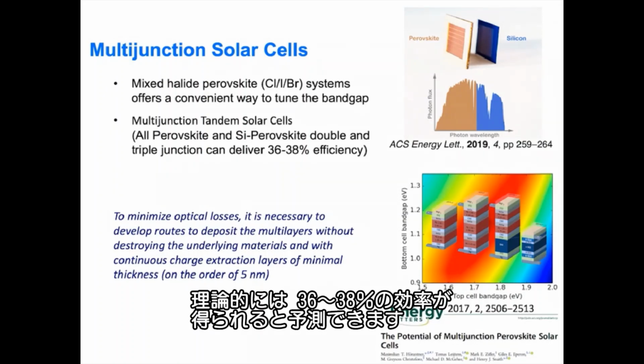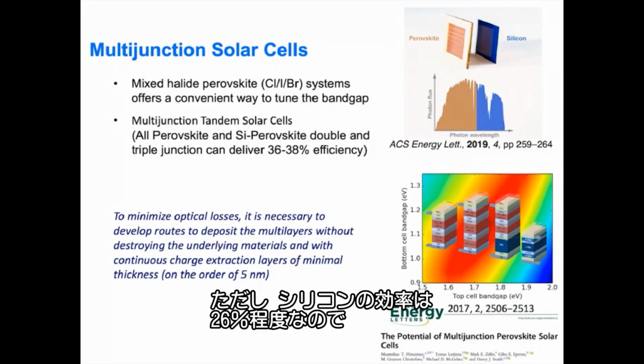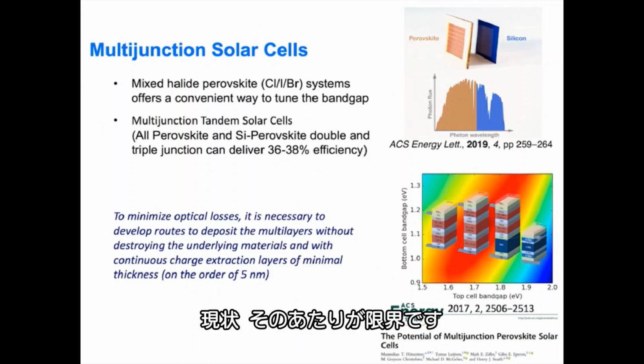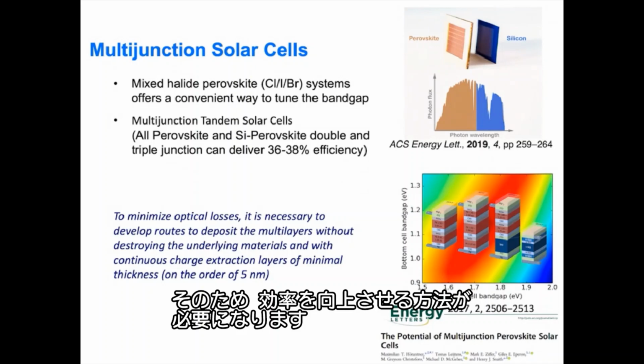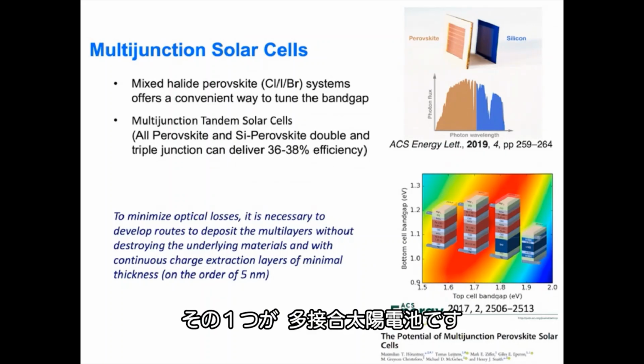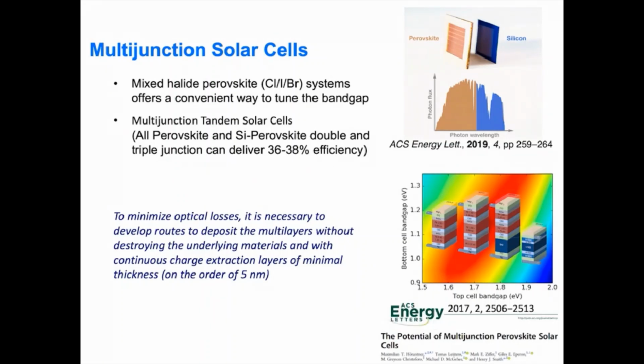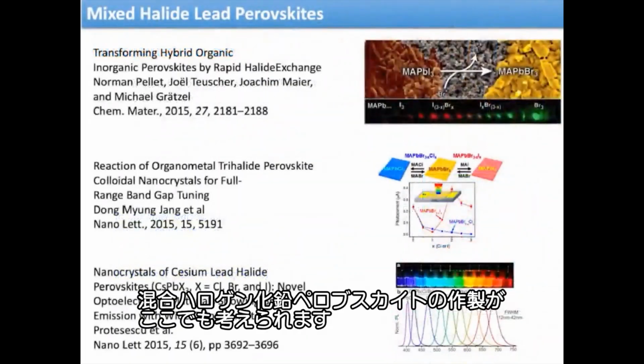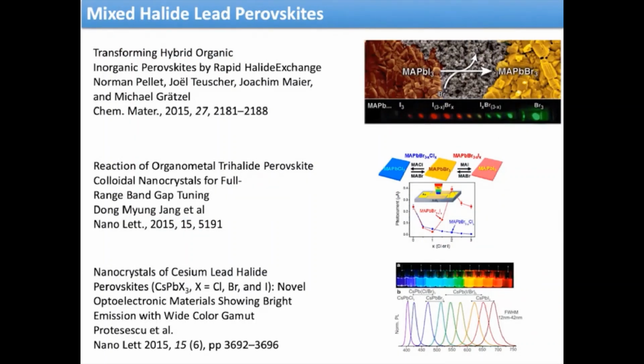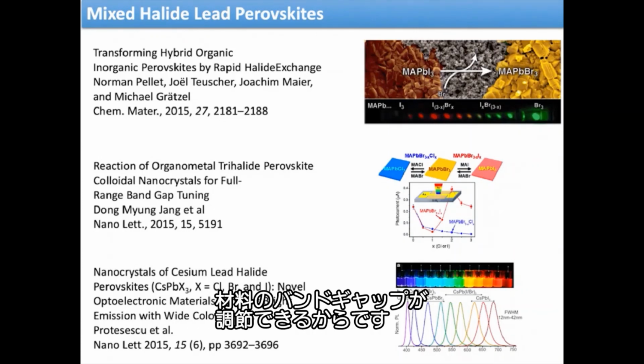The theoretical prediction is one should be able to get 36 to 38%. Note that silicon has only 26%. It is basically stuck around that value, and we need to find ways to improve the efficiency, and the multi-junction solar cell is one of these ways to make it. So that comes to the aspect of, again, making mixed halide lead perovskite, as one can use the composition of halides to tune the band gap of the material.